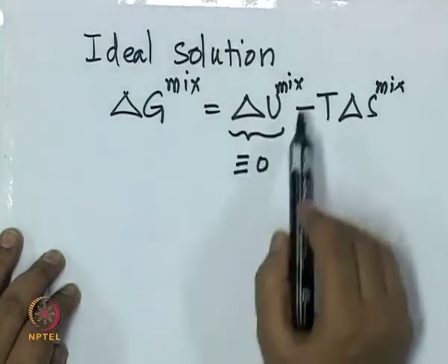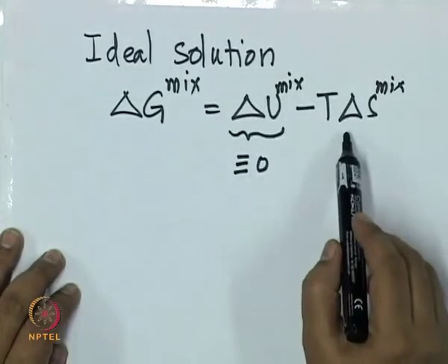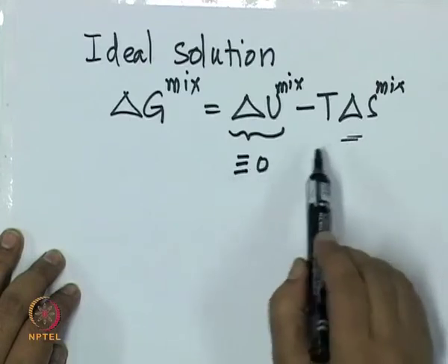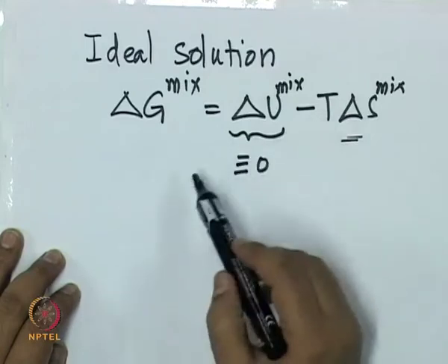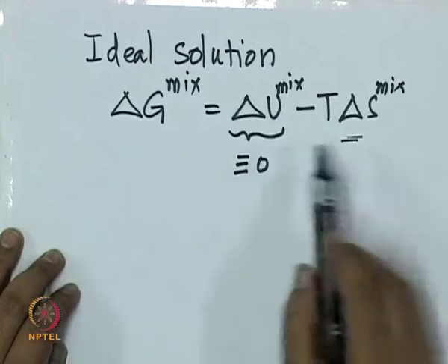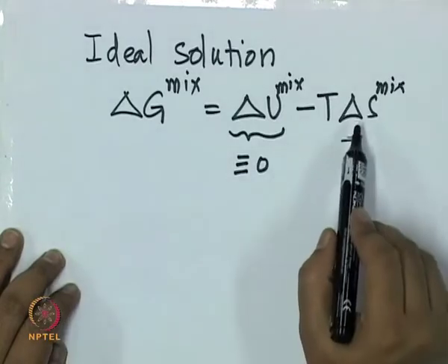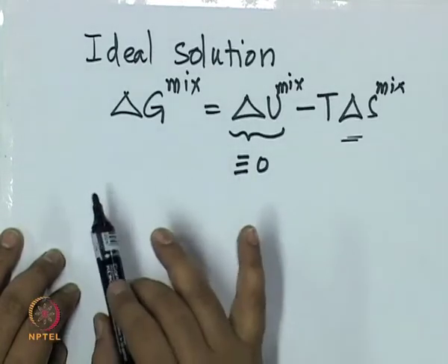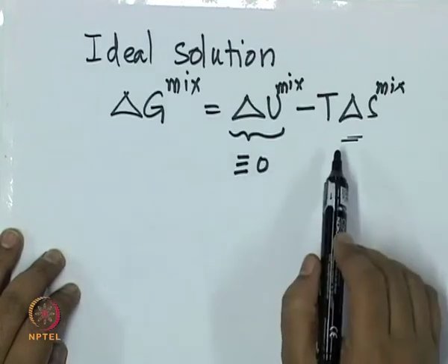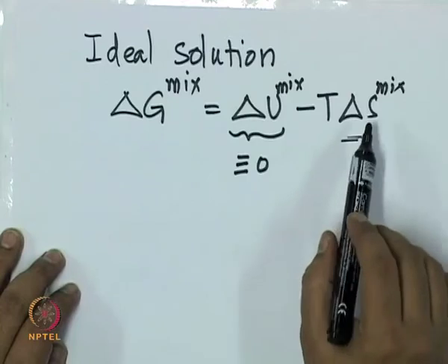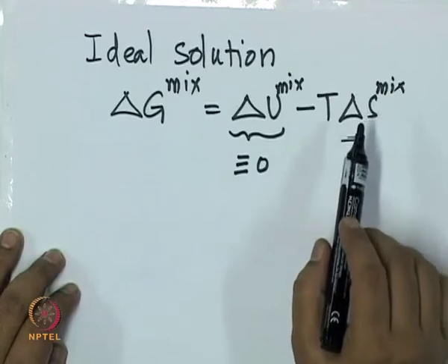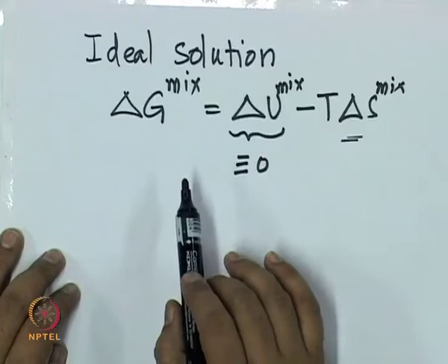So, for now let us assume that it is not there, and now we also want to know what is the change in entropy. So, that can be multiplied with the absolute temperature in which the system is kept, and then we will know how much is the free energy of mixing. We make an assumption in majority of the cases that we will discuss for these kind of alloy models, that the only contribution to the entropy comes from the configurational entropy.